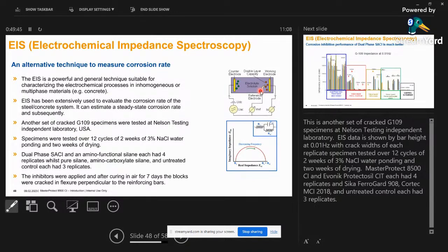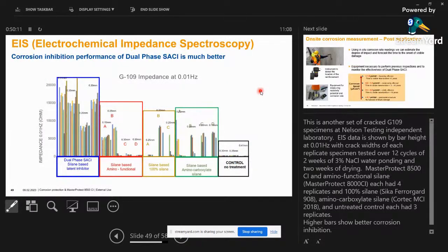Then this is an impedance spectroscopy test, another test that was performed on this, again with severely induced chloride ion penetration into the reinforced concrete structures. And the impedance measurement was taken. Why I'm showing a glimpse of all the tests that have been done is to just give you an idea of how this simple liquid performs when compared with other types of technologies. So if you look at its effectiveness, it's very high compared to the other ones.